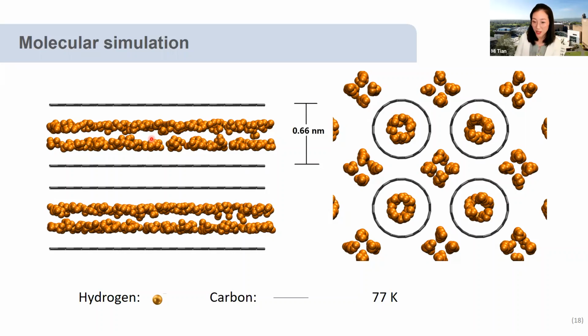Where I am, okay. Yes, molecular simulation. We can see these are slit pore shapes with a pore size of 0.66 nanometer. In this pore size and pore shape, we can see hydrogen molecules, the golden spheres, form highly ordered two layers. The space is just too narrow, so hydrogen molecules cannot move around. They are fixed on site. So that's why the neutron can scatter with these fixed hydrogen molecules.